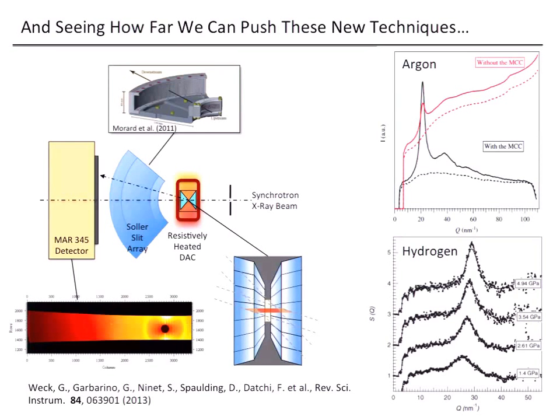And we pushed this to hydrogen, which is sort of the ultimate test because it's the lightest and hardest element to get any signal from. This data is still pretty crummy, but it shows there is a peak, which is sort of the encouraging thing, and we see the peak evolving in pressure. So this was good proof of concept that we can actually apply this technique and look at coordination changes in chemistry in these liquids to start looking for these complex or more subtle liquid transitions.